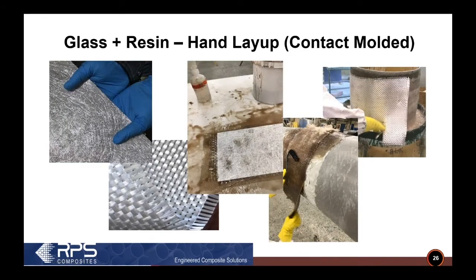So when you're making a product, and again, this would apply to tanks or piping, you take the glass and you saturate it with resin, and you have two ways of making something. Generally, one is called hand layup or contact molded, and this is the most basic way of making anything out of fiberglass. You catalyze the resin and take your glass reinforcement, and in the middle of the screen, you can see the person has saturated that glass reinforcement with the catalyzed resin, and on the right-hand side they're going to apply that to, in that case, a butt joint.